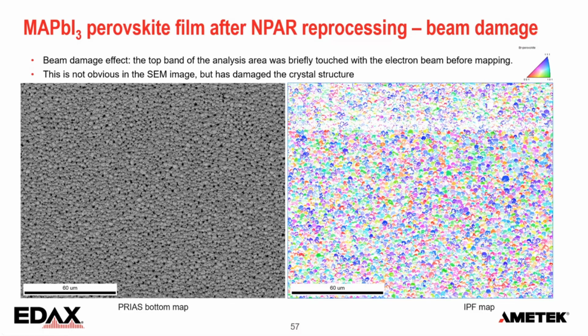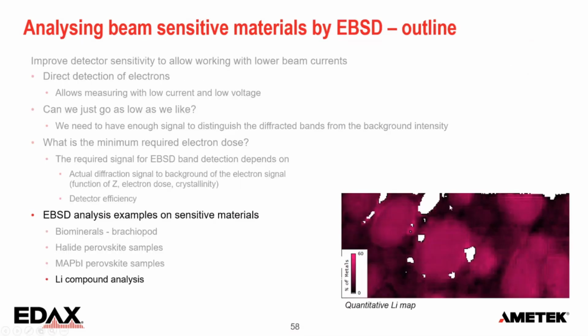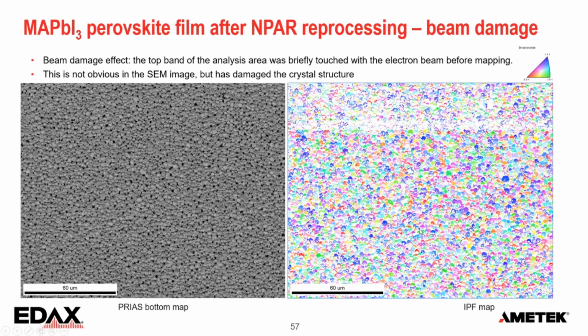So what you need to do on a material like this is go to an area that you're going to sacrifice, optimize the beam, focus everything, zoom out to the magnification you want to use, move the stage, and immediately start mapping. Always start mapping on a clean, fresh area, and that should allow you to get good indexing results.